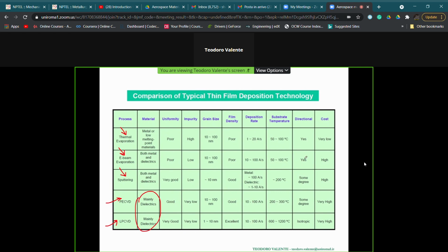But please remember again that, with respect to what we have seen for the thermal spray technologies, we have very, very low deposition rates. Generally speaking, thermal spray technologies, HVOF or plasma, have different features, but just to give you a rough number, they are able to spray kilograms per hour. Here we are talking, in the best cases of CVD, PVD being lower, of deposition rates which are usually less than 1 micron per hour. And this concludes our discussion about surface engineering.